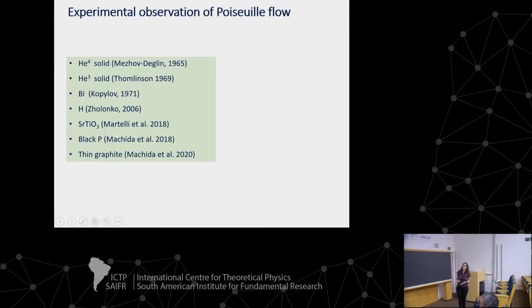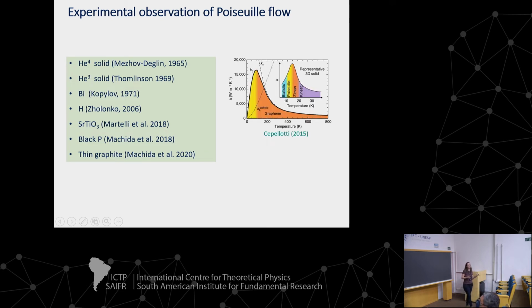To give a framework, there are really few solids, some very special materials, that show this behavior. Recently, after our observation in STO, it was also observed in black phosphorus and thin graphite. We might ask ourselves if we were not looking carefully into this previously, not because maybe it was not there. I can say myself that I measured the thermal conductivity of graphite a few years ago, and I didn't notice that. So probably now we have a fresh look, and we are more carefully analyzing and looking for this special regime. And what also makes this investigation attractive is that there are some works.